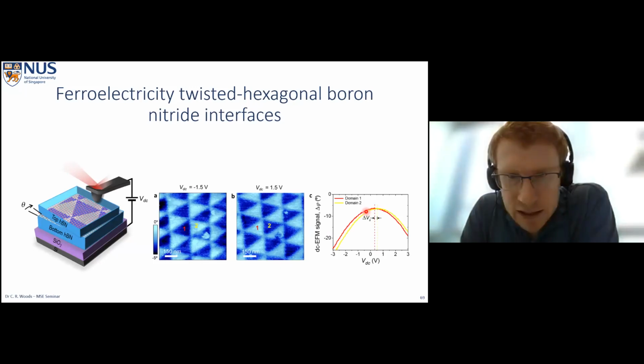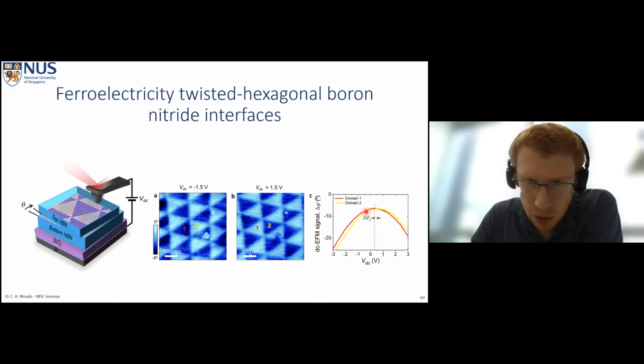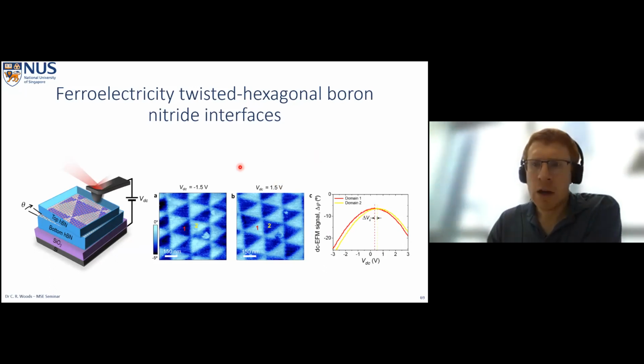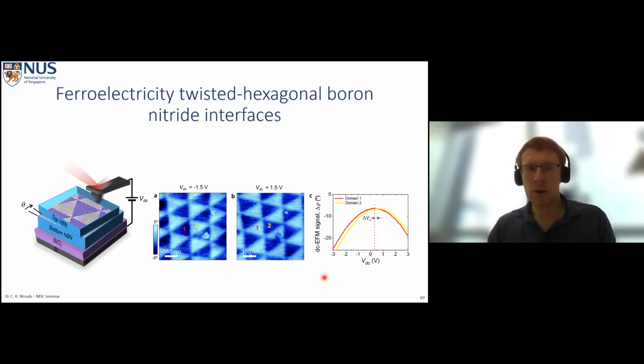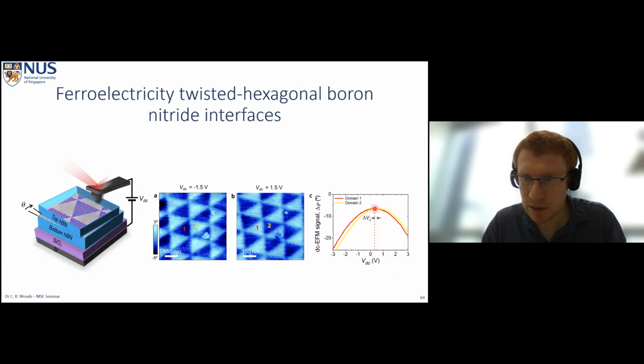Okay, so now we understand why we're seeing triangular domains, AB versus BA. Now we need to understand why we see them at all. What is the contrast that we're observing in our EFM signal? Because we don't see anything in topography, but we do see it in electric force. So what we do for this is we measure the force on our tip as a function of the DC voltage between our silicon and the tip itself. So we're measuring the electric field through our sample, and we change the DC voltage. And of course, this will depend on the work function difference between the tip and the silicon. But ultimately, we can make the force minimum when the potential difference between the tip and the silicon is 0. So when the potential difference is 0, we get the force at a minimum.